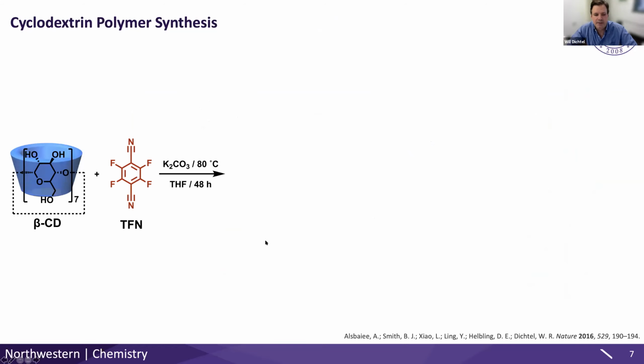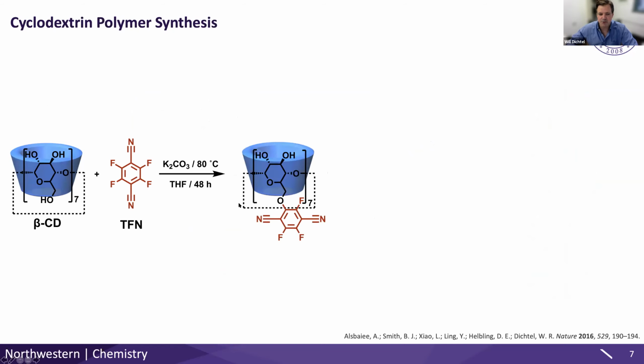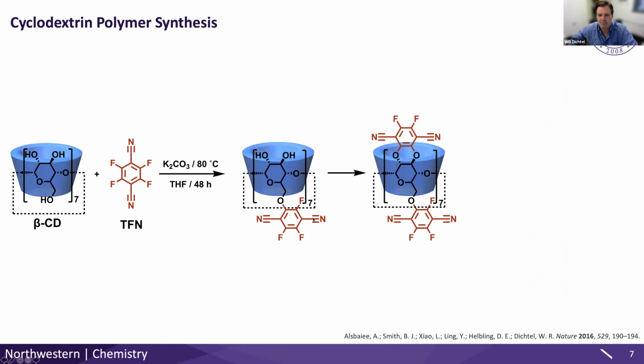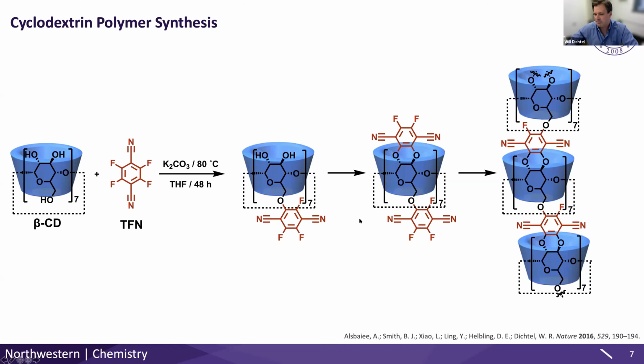And so the way we do this more technically is to take cyclodextrin and another molecule called a crosslinker, shown here in red on this slide. This specific cross-linker is called tetrafluoroterephthalonitrile, which is kind of hard to say, so we'll just call it TFN. Under particular conditions that are meaningful to an organic chemist, these will start forming bonds between some of the oxygens of the sugar and the TFN. That will happen multiple times until finally you can build up this whole gnarled-up network where we've linked all of our cyclodextrins into kind of an infinite structure.